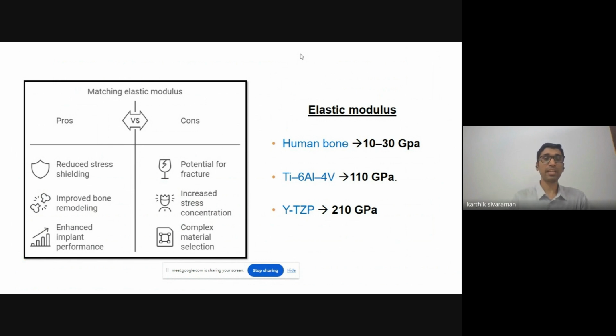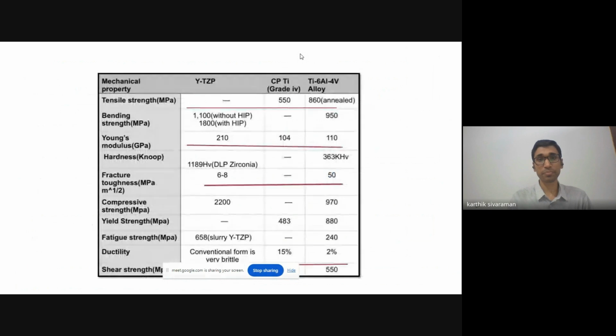Now, when we have an elastic modulus which is closer to that of bone, we do not see any stress accumulation within the implant. When we take an implant material which has a greater elastic modulus and greater difference compared to that of bone, you will have a stress shielding effect, and as a result, the implant material will be prone to fracture, and it will also result in an altered bone remodeling process. So if we analyze this data objectively, we see that the titanium alloy has a much more favorable result over a long term due to this major difference.